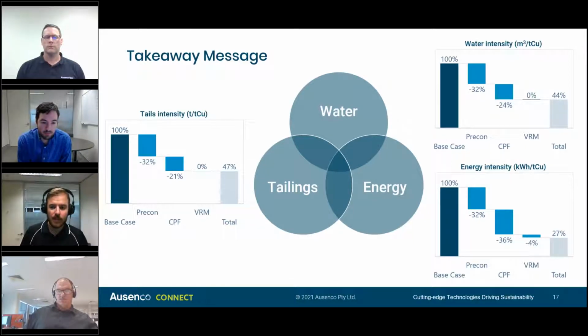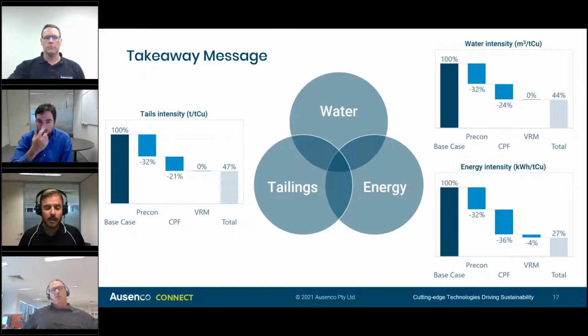I've just plotted here the tails intensity, the water intensity, and the energy intensity per metal product. In this case, I'm referring to copper. And I've just shown the relative potential of each of the technologies that we've looked at: the pre-concentration, the coarse particle flotation, and the vertical roller mill. And you can see in terms of tails intensity, the pre-concentration can reduce your tails by 32%. Coarse particle flotation can reduce those tails by about 21%. And that's a total reduction of over 50% of tailings production, of wet tailings storage that's required.